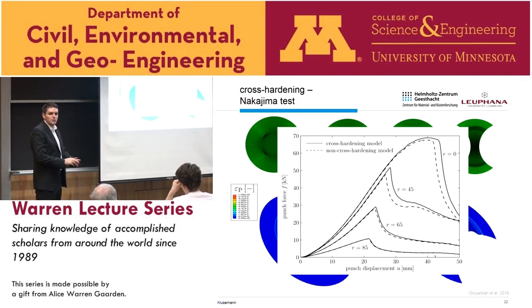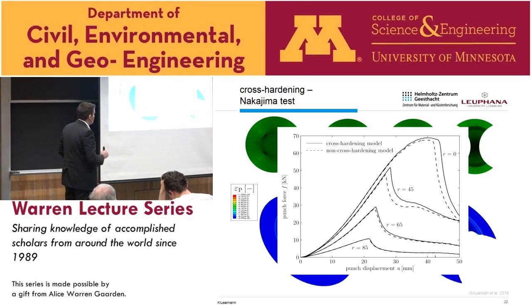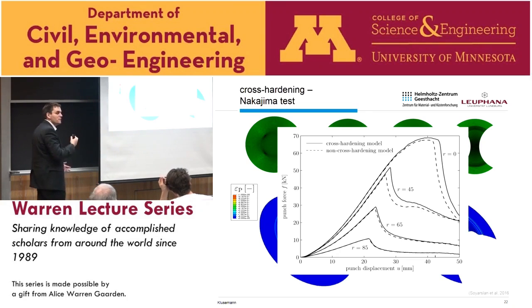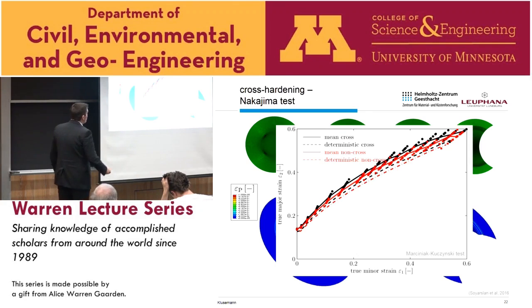And interesting now is the difference between the cross-hardening and the non-cross-hardening model. What you can see is, in the uniaxial case, there's no difference. You would not expect any difference there, which I will show in a minute why. But you would expect strong differences in this case. And this is also visible, of course, in the simulation. The cross-hardening seemed to actually increase the forming limit capabilities of the material, at least from a simulation standpoint.